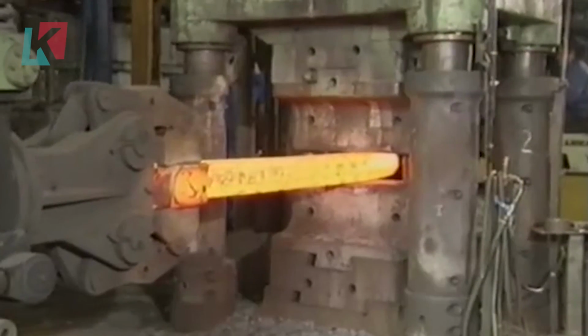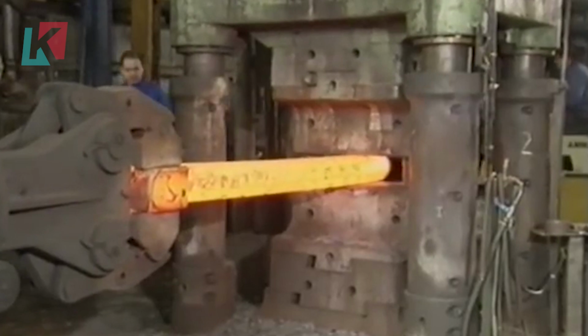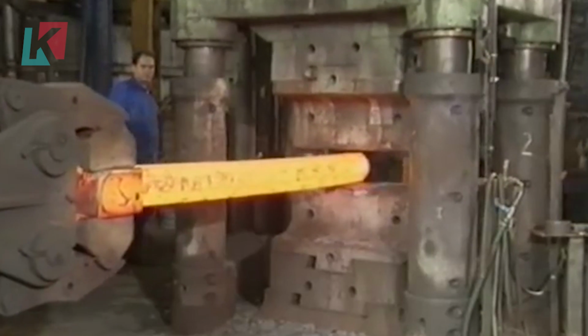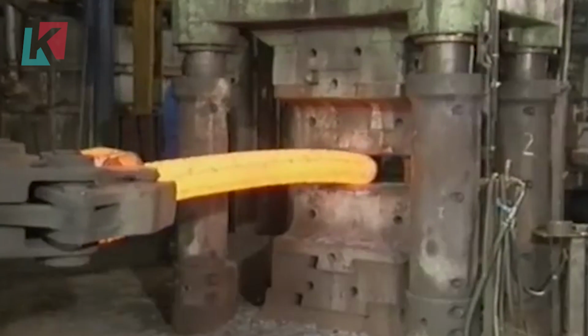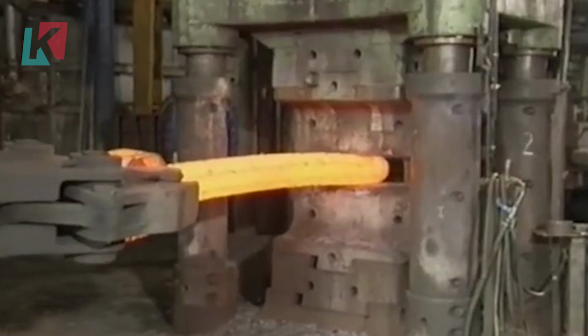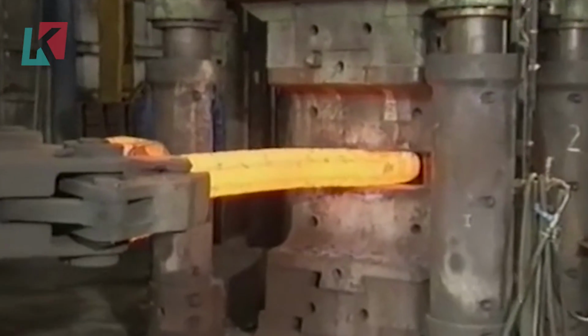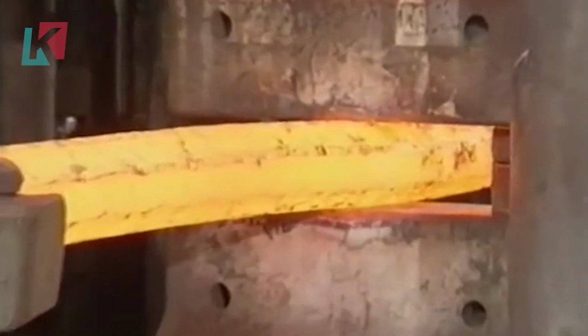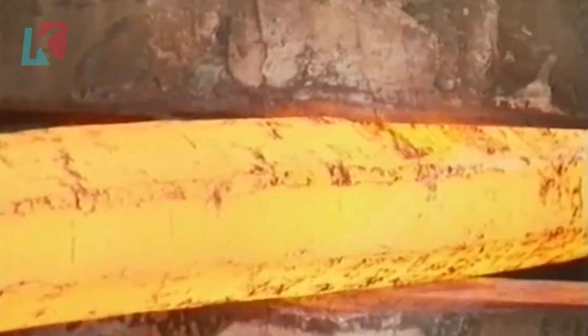If the steel temperature drops below 1,100 degrees Celsius, the piece must be reheated. Infrared pyrometers continuously monitor temperature, but the experienced forger can judge temperature by color. Bright orange indicates proper forging temperature, while dark red means reheating is needed.